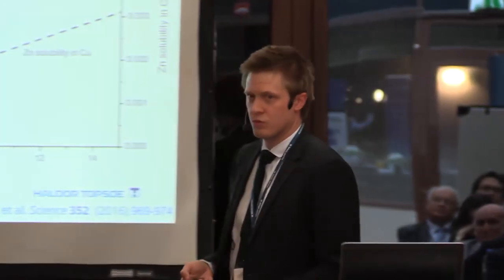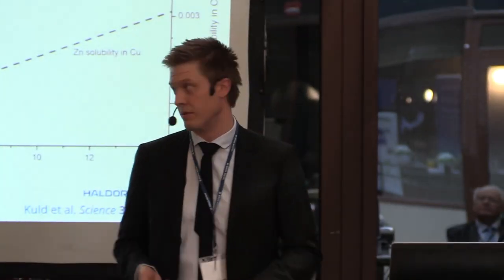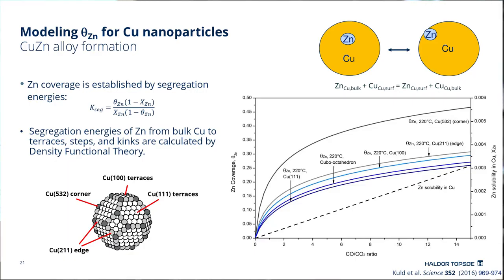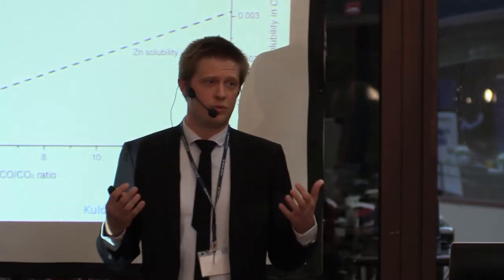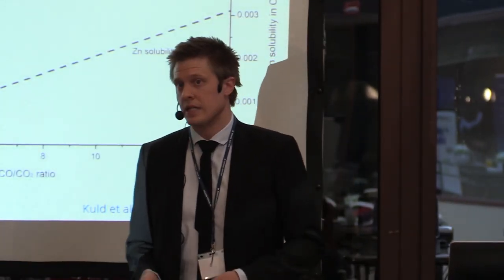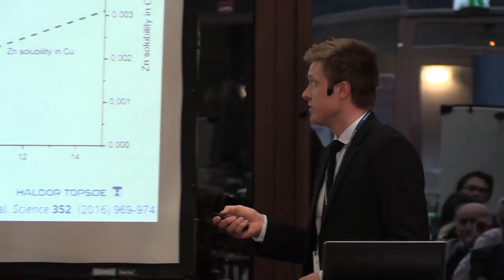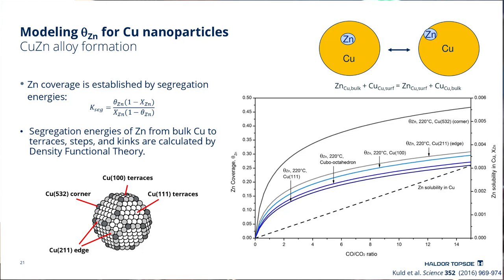The next question is, of course, what will happen with the zinc once it's inside the copper? Zinc in the bulk of the copper particles will be in equilibrium with zinc on the outside of your copper particles. And by knowing the segregation energies of zinc to the surface, you can calculate the zinc coverage based on the reduction potential. So how can you calculate the segregation energies? We did that by means of density functional theory. And such a nanoparticle has a lot of different sites, so we needed to calculate the segregation energies to all these different sites.